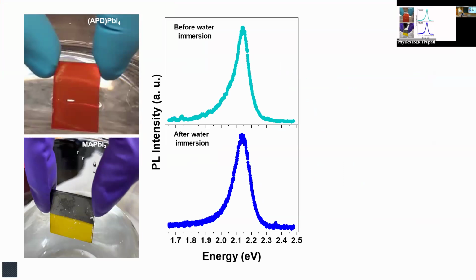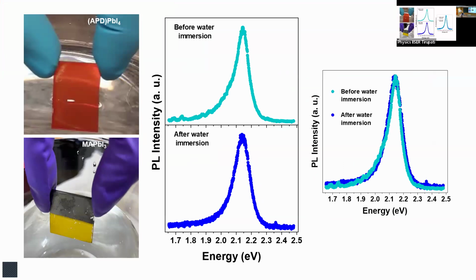And also the water stability, which was the original motivating force. You can see if she takes MAPbI3, the three-dimensional object instantaneously comes through as lead iodide. Here you can dip it there for hours together, nothing happens. In fact, we tested it by looking at the photoluminescence before putting it in water and after, and superposing them one on top of the other, and you see absolutely no effect. So it's extremely well preserved when dipped into water. So they have very good stability.